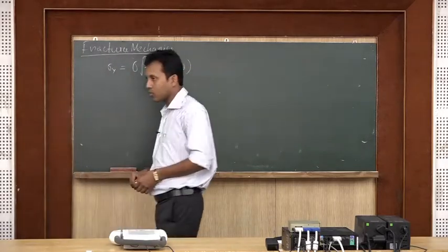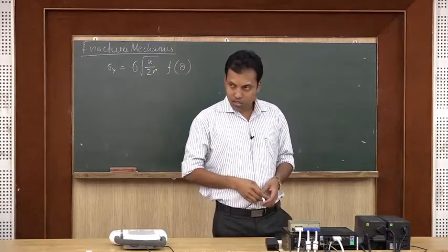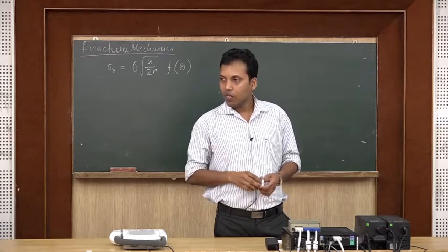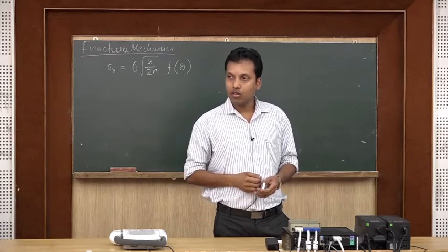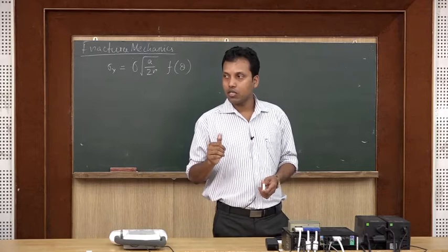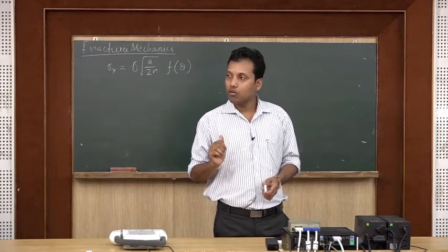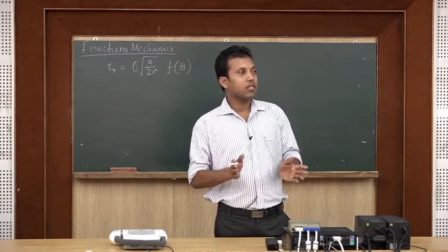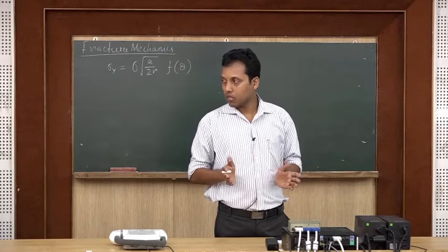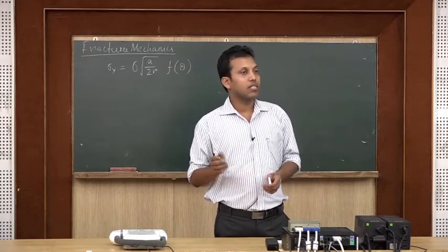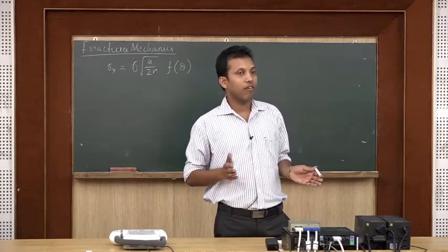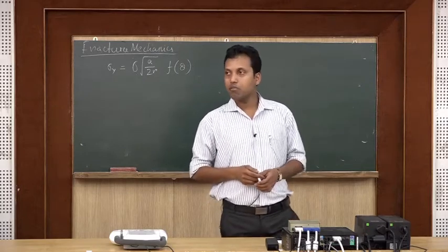function of theta. Okay. So, in this we have said something like stress intensity factor, okay, and stress intensity factor based on a particular geometry, it is sigma root pi a, which we denoted as K1 for mode 1 loading. Okay. The value of this K1 may vary based on the nature of the crack which is present. Okay. That is known as the geometric factor. That means the geometry of a crack may vary, and so this value will vary, isn't it? So, those things we have seen.